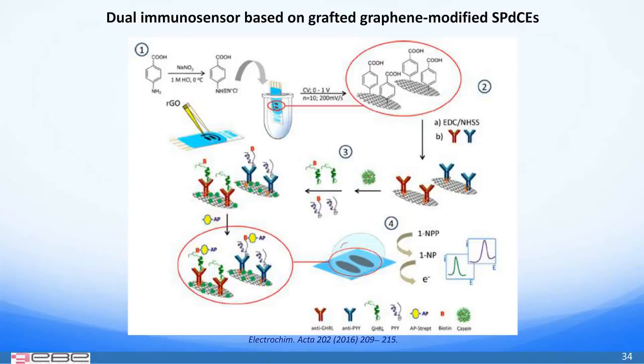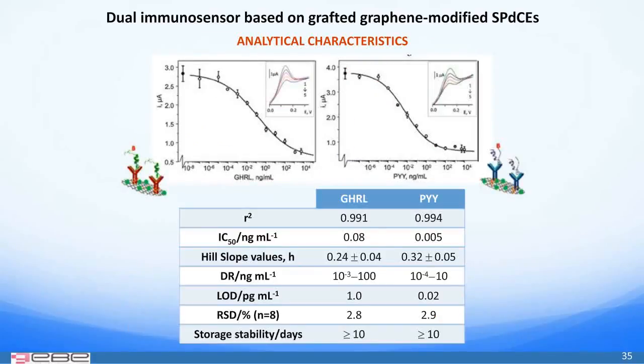The determination of each hormone was performed by direct competitive immunoassays with the corresponding biotinylated hormones for the capture antibody immobilized. After labeling the attached biotinylated hormones with a commercial polymer of streptavidin alkaline phosphatase, the DPV signal obtained in the presence of 1-naphthyl phosphate was monitored. Under the optimized working conditions, the analytical characteristics summarized in the table were appropriate for the determination of both hormones at clinical levels in serum and saliva samples.